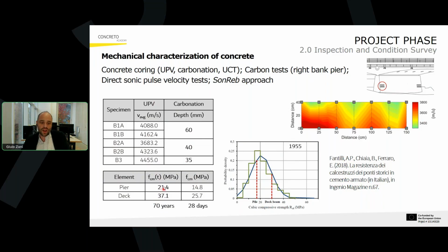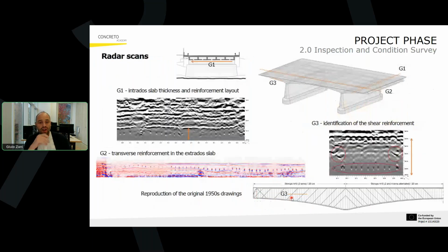So after 70 years, we have these two strengths. The pier is much more porous and of less quality concrete than the deck. But we were able to go back to the time of construction, so just 28 days after casting, thanks to some formulations that you find, for instance, inside the Model Code 2010. And you see that we obtain some strengths which are in line with the strengths of materials in the 1950s. This is something extracted from a database which was built by the Politecnico di Torino, thanks to the collection of several certificates issued by university labs. And so for different decades, we have an idea of the range of strength which was actually used.